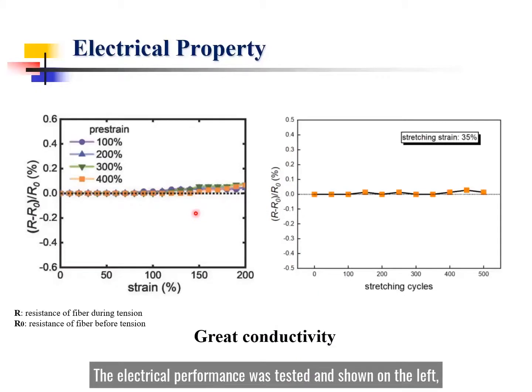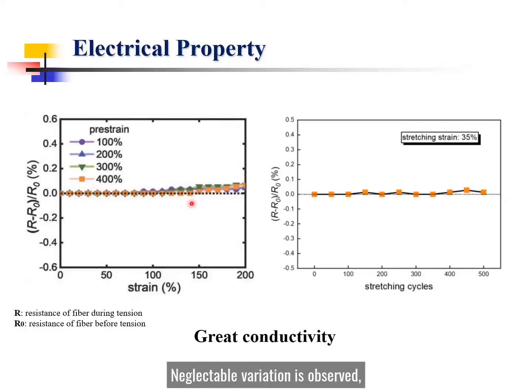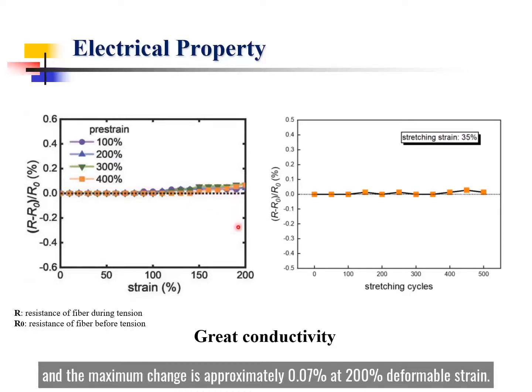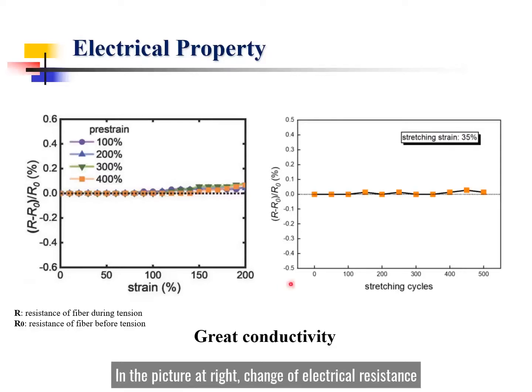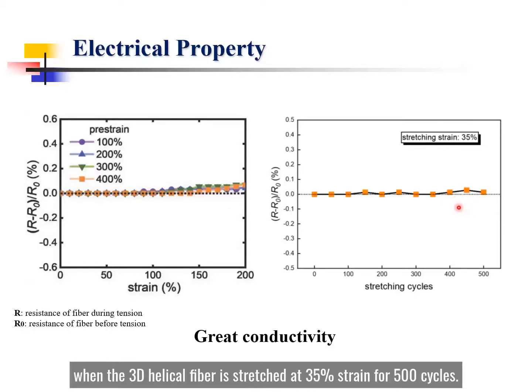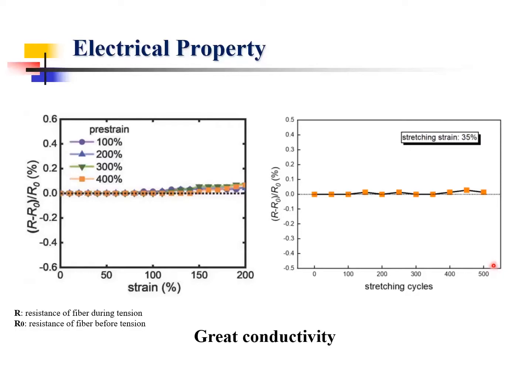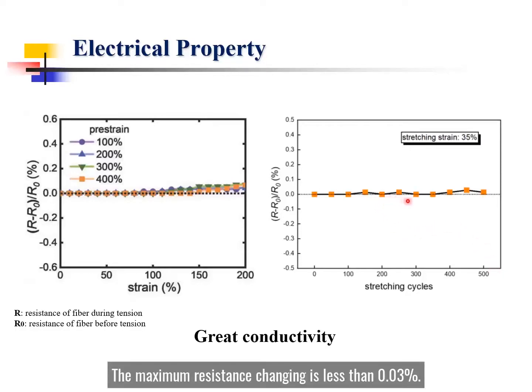The electrical performance was tested as shown on the left. Negligible variation is observed, and the maximum change is approximately 0.07% at 200% deformation strain. In the picture at right, the change of electrical resistance is shown when the 3D helical fiber is strained at 35% strain for 500 cycles. The maximum resistance change is less than 0.03%.